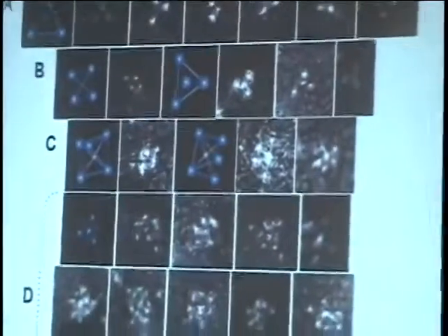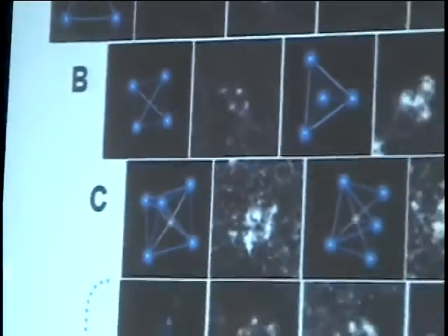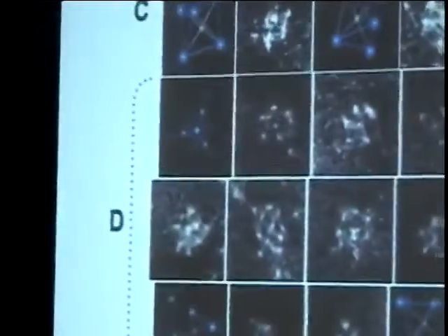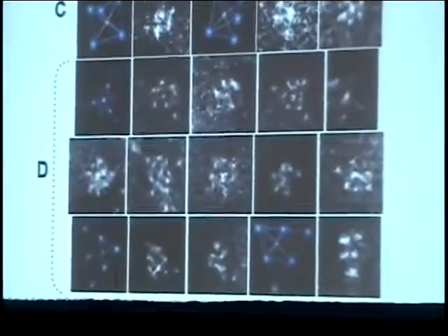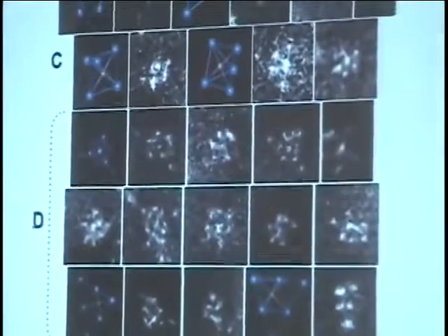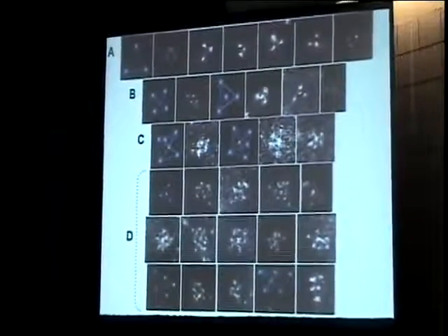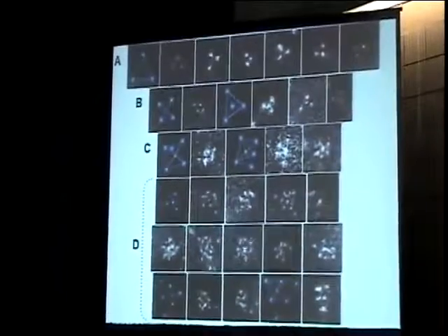So what we've done is we've taken a sample, made it from the triosmium cluster, treated in helium to fragment the clusters, as I mentioned before, then treated in CO to start forming larger clusters, and we chose the conditions to get a mixture. So not just Os10 or Os5, but a mixture. And then looked at that sample in the aberration-corrected STEM.